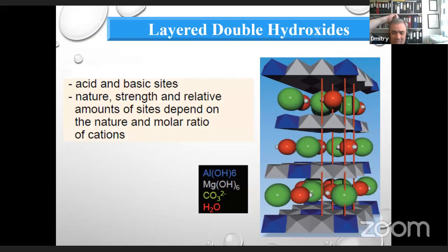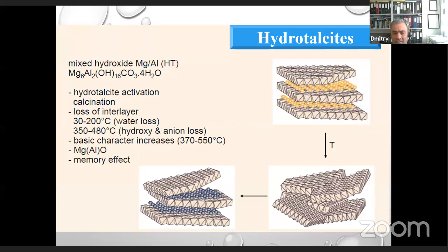So these hydrotalcites, layered double hydroxides, have both acid and basic sites, and the nature, strength, and relative amount of sites depend on the nature and the molar ratio of cations present in these materials. What is important is that hydrotalcites should be properly activated, so thermal treatment or calcination is important, and the basic character of the materials increases when we elevate the temperature. In some cases, non-thermally treated hydrotalcites are not catalytically active at all, and then we need a certain thermal treatment to get this catalytic activity.